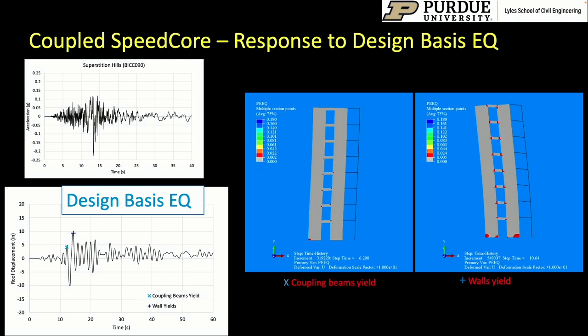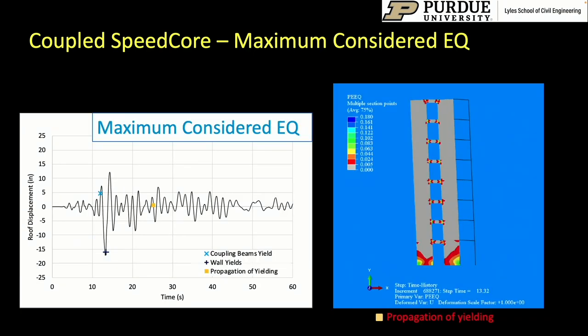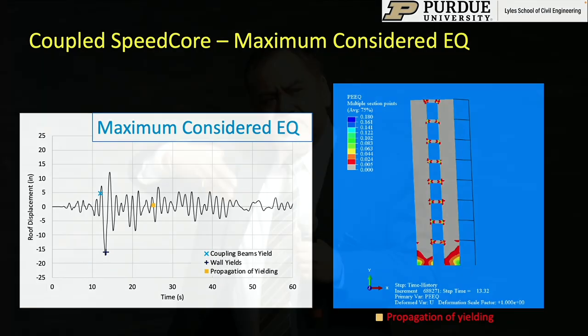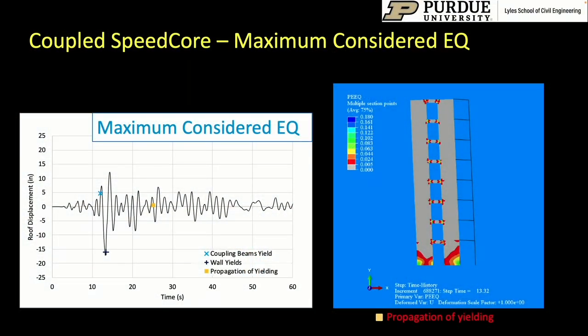When you make the earthquake larger by changing it to the maximum considered earthquake, the response shows that you get more yielding of the coupling beams and it propagates along the height of the structure, which is what we want. The more you dissipate plasticity along the height of the structure, the better the earthquake behavior, the better the ductility, and the larger the R factor. So we were able to achieve that by spreading the plasticity along the height. You do still get some formation of plasticity at the base of the walls.